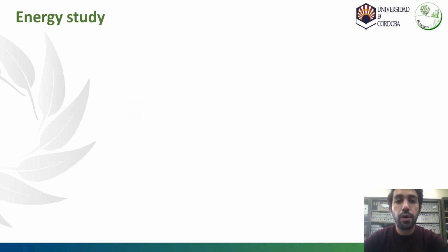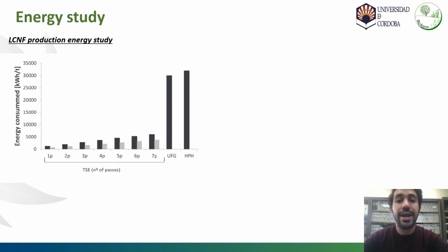One of the main problems in the production of cellulose nanofiber is the high energy demand that this kind of process requires. We analyzed the energy consumption required to obtain the different types of lignocellulose nanofiber studied in this work, and we observed that the homogenization process requires 32,000 kilowatt-hours per ton, the ultrafine grinder, the Masuko, 30,000 kilowatt-hours per ton, and the extruder only 6,000 kilowatt-hours per ton.